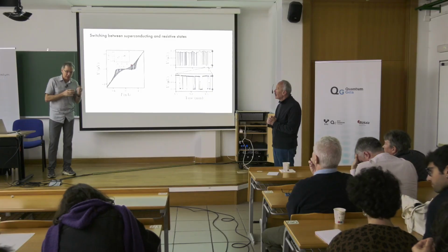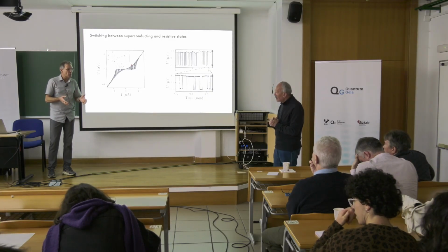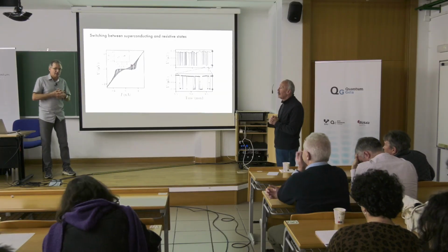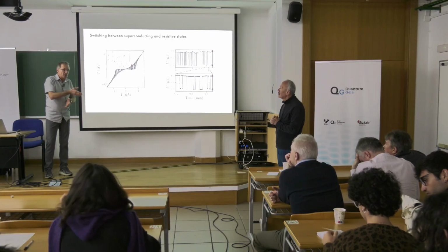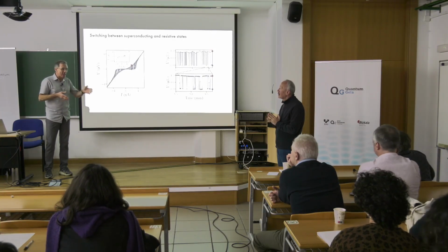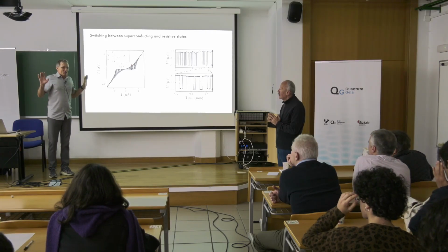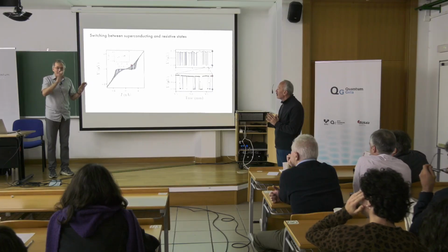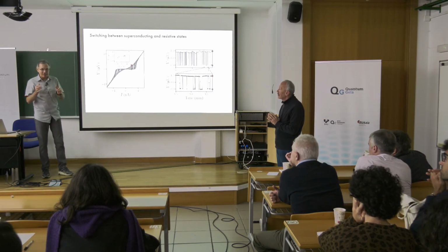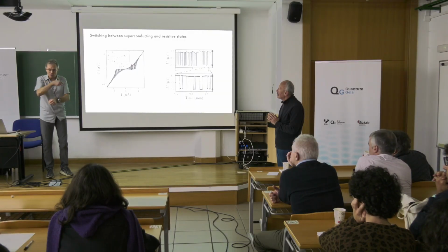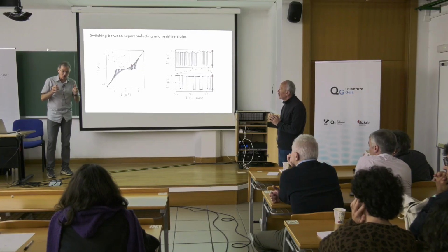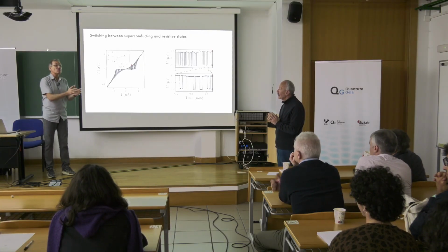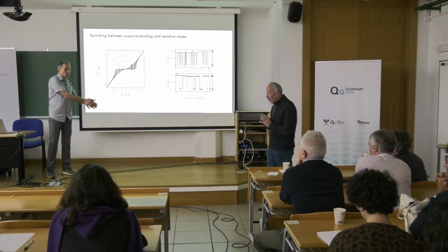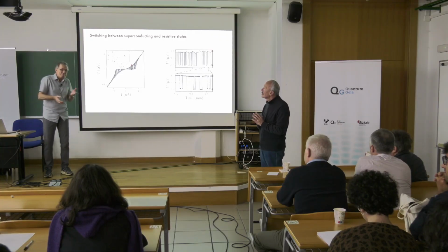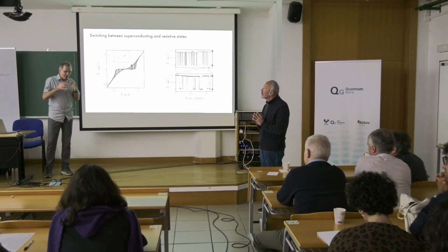There are two things there. Even for usual materials, like superconducting properties and transition temperature, to predict which material should be superconducting and which not is very hard, and it's much better, after we know the transition temperature, to fit our theory which predicts that. But if you don't know, then to predict, even for the simplest lithium, which is as close to hydrogen, the simplest, for many years it was not superconducting, now it is superconducting, so it's very hard to predict.